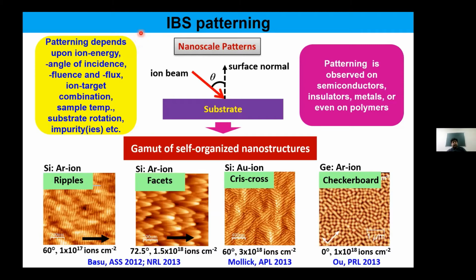And what we are seeing here, next frame, is again the same ion energy, same sample, but the incident angle is different. We get to see these beautiful facets, nanoscale facet formation on the same sample, under same experimental conditions, but with only one change, and that was the angle of incidence of these ions.